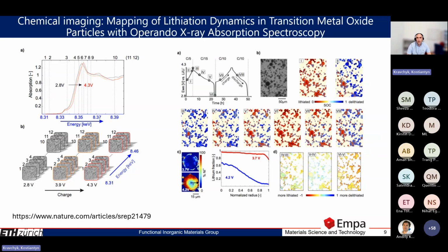And from this information, you can recalculate, of course, the lithiation state of your cathode, and understand the kinetic limitations which you usually have inside of your cathode, especially if the cathode is quite thick. So you might have some inhomogeneities in the lithiation behavior of thick cathodes.